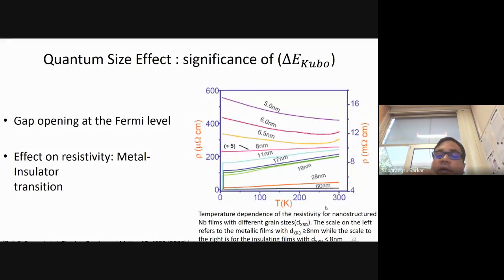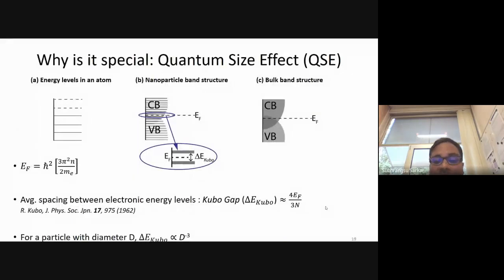In the graph on the right, you can see that when the particle size is about 60 nanometers, then the resistivity is the lowest. And then as we reduce the particle size, the resistivity goes higher and higher. Now, one might argue that it is happening because the material is gathering defects or grain boundary scattering or something like this. But when we reduce the particle size below 11 nanometers or 8 nanometers, the resistivity curve takes a complete upturn at lower temperature, which is happening because of a gap opening at the Fermi surface. This cannot be explained by grain boundary scattering anymore. This is happening because of the gap that we mentioned here.